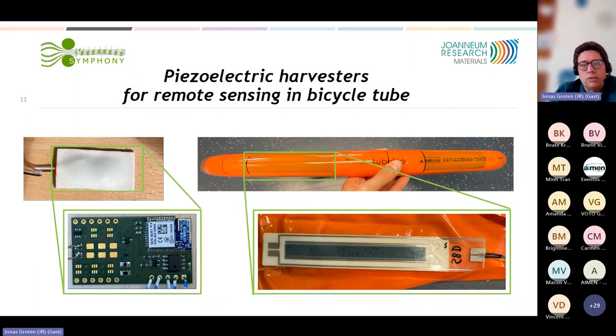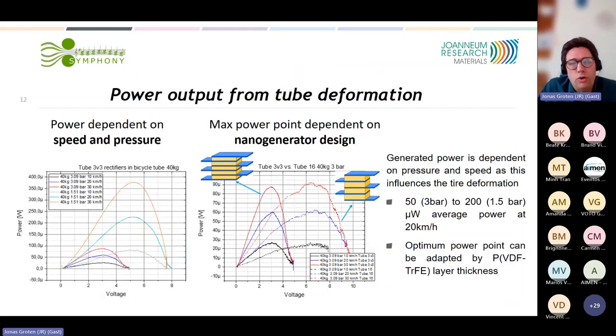Putting the electronics in such a TPU foam is a very good solution here. And what I really want to point out, which is a lesson learned from our project, when it comes to energy harvesting, we of course had here the possibility to really structure the PVDF layer thickness, the sizes, and the cantilevers. And it's, in my opinion, really important for each application to really tune the cantilever or the harvester to the mechanical input, as we can otherwise lose a lot of energy. As you, for example, can see here in this right diagram.